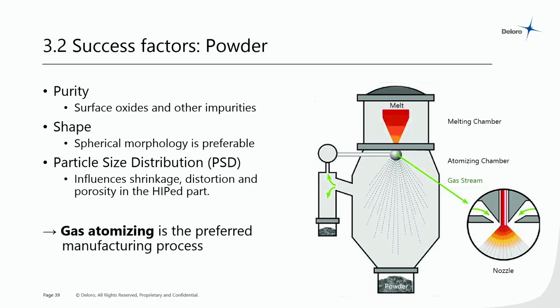The other big success factor is powder. The purity is important because surface oxides and other impurities don't disappear. When you HIP a powder, those prior particle boundaries are still there. Those oxides don't go away necessarily. So purity is very important.